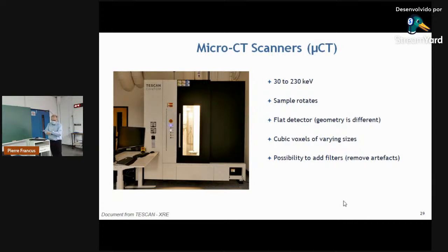The last scanner I'm going to talk about is the MicroCT scanner, and this is a little bit different compared to the medical CT scanner. Here, the sample is laid vertical, and it's the sample that is rotating. It's not the source and the detector. The source and the detector are fixed. With this setting, you can go from 30 to 230 kV, which means that you have more power to go through denser material. Depending on the settings, you can choose the size of the voxels. They are cubic, not rectangular like for the medical CT. For very small samples, you can go down to 3 microns with this model, up to 80 microns, for instance. For a regular sediment core that is 8 to 10 centimeters in diameter, you can get 15 micron resolution.